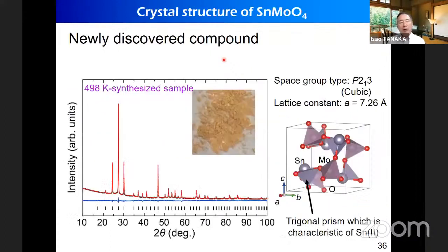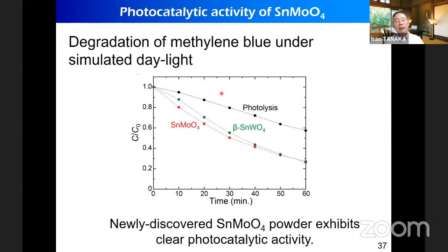After some trial and error, we succeeded in synthesizing this yellowish powder. And the crystalline phase included in this synthesized sample is only a single phase. By Rietveld analysis, it is confirmed to have this crystal structure, which we found is identical to what we predicted by theoretical calculation. And for the photocatalytic activity, we made a simple test by degradation of methylene blue under simulated daylight. So this is the degradation behavior with time.